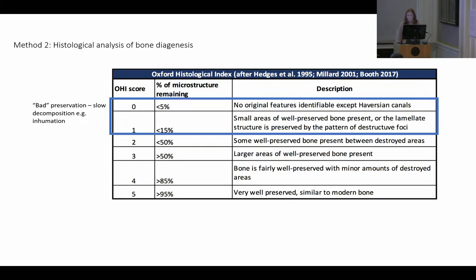So a score of 0 to 1 is considered bad preservation and might suggest that the body decomposed slowly. So this is what we would expect in an inhumation that was buried in the ground shortly after death. And then a score of 2 to 3 is a middle-ranging score, and this suggests that the body decomposed quickly but not super fast. So this may be someone who was placed in a covered pit so that scavenging animals couldn't access it, but it was more aerated and easier for insects to access. Or it may be that the burial was delayed a bit.